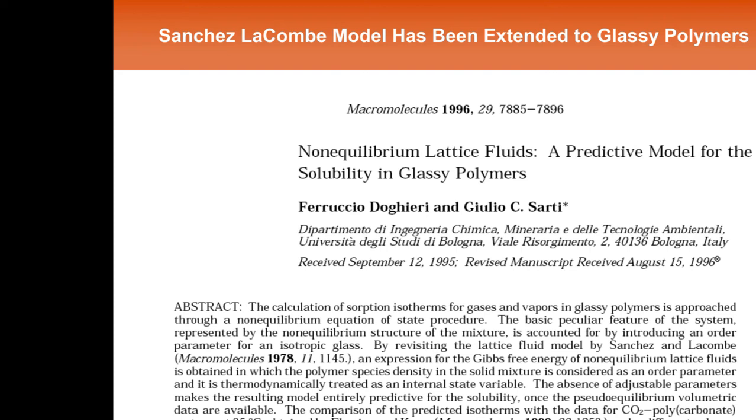Can you imagine the nerve? It's heartless, right? So here you see standard dual mode behavior, and then you put just a little bit of butane in that gas mixture. It sorbs into the polymer, effectively fills the Langmuir sites, and the only thing that's left for methane is it can sorb into the Henry's law sites, but it can't get into the Langmuir sites.